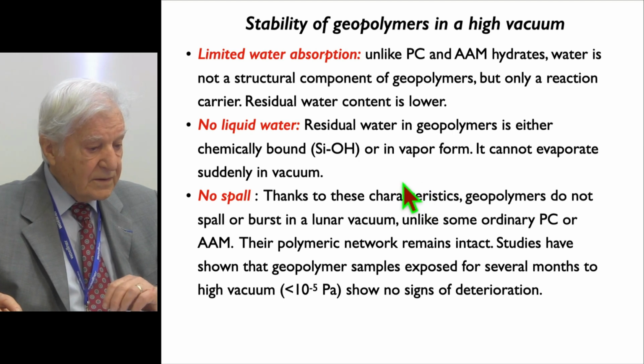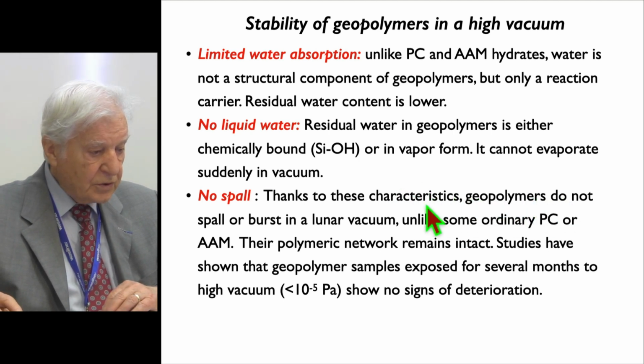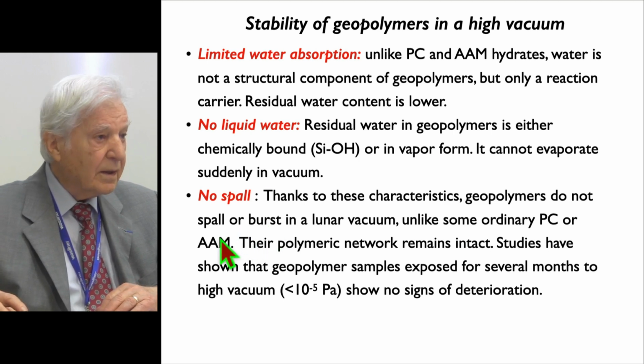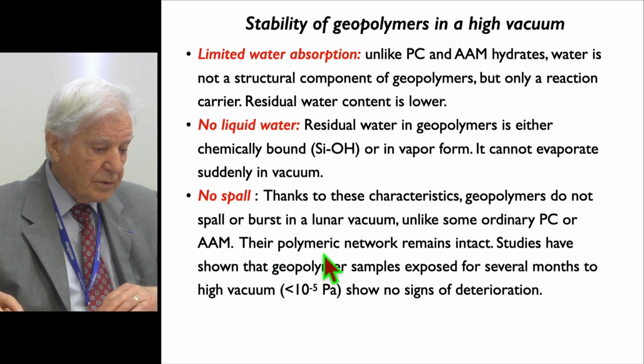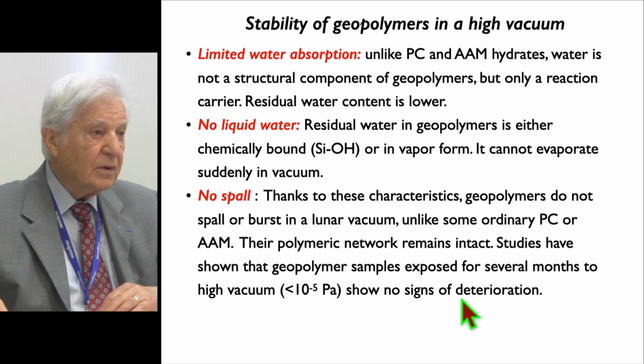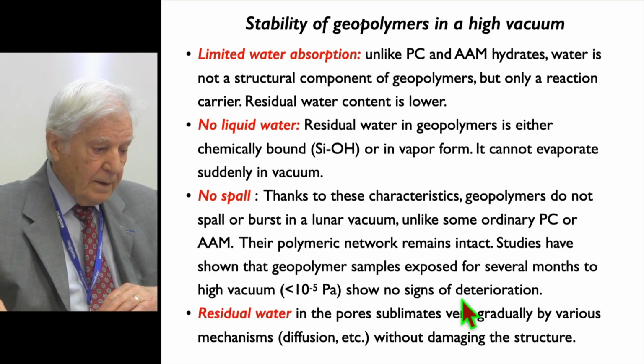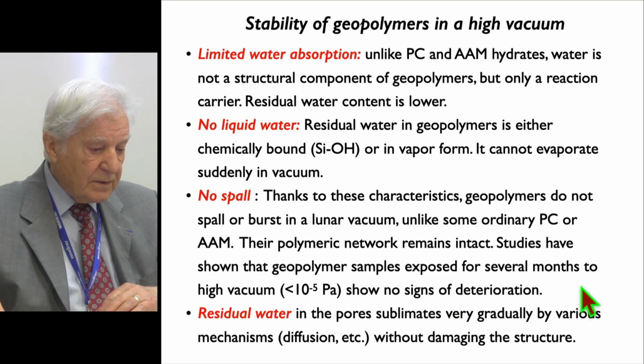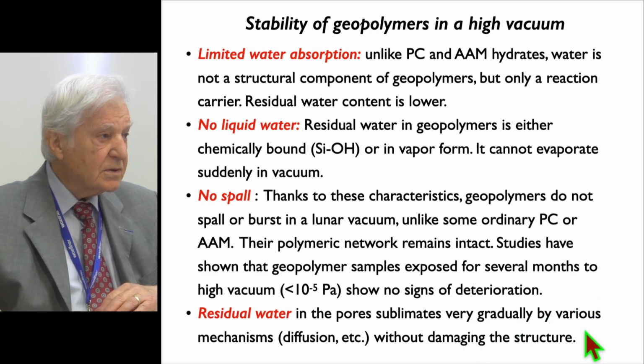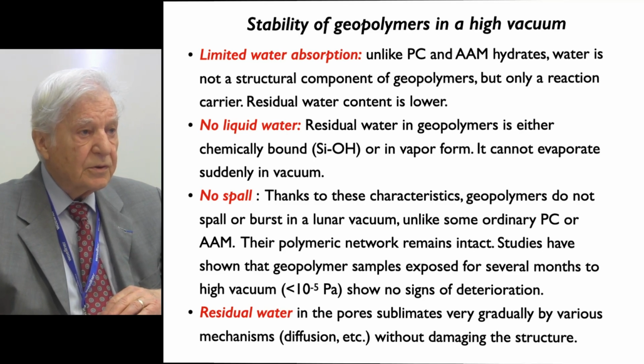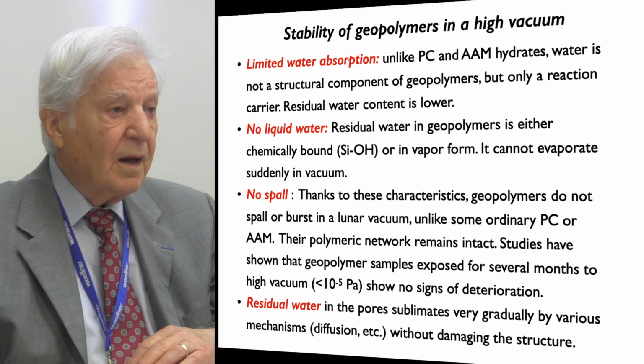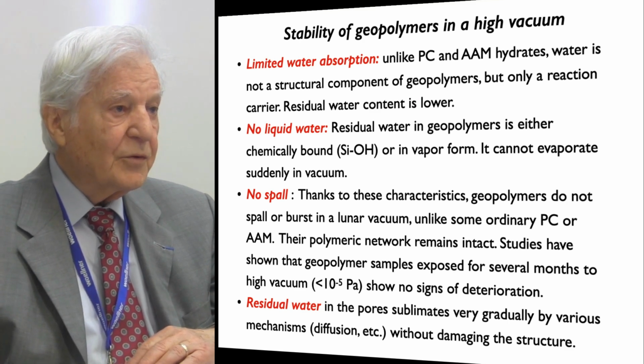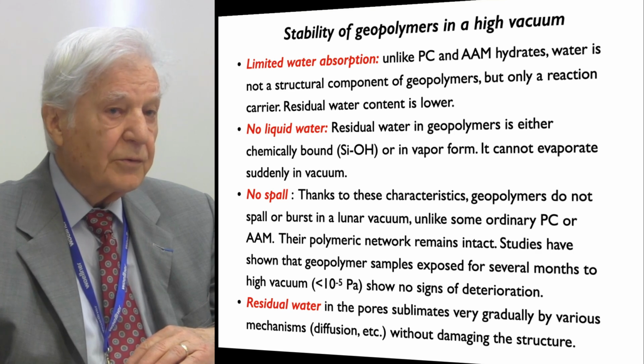No spall. Thanks to these characteristics, geopolymers do not spall or burst in a lunar vacuum, unlike some ordinary Portland cement and alkali-activated materials. Their polymeric network remains intact. Studies have shown that geopolymer samples exposed for several months to high vacuum show no signs of deterioration. Residual water in the pores sublimates very gradually by various mechanisms, such as diffusion, without damaging the structure. All these properties are not only valid for the moon, but they are also valid for our material used on Earth.